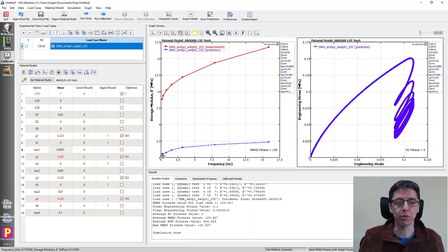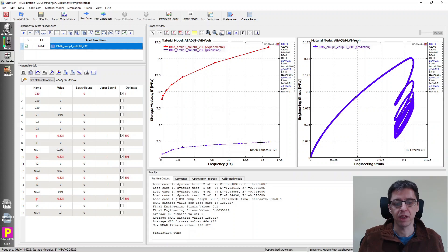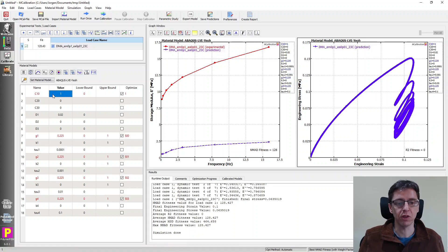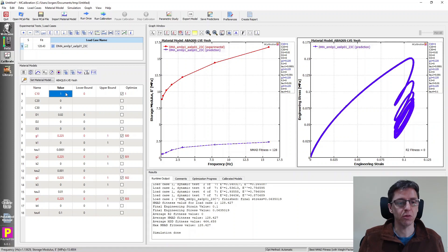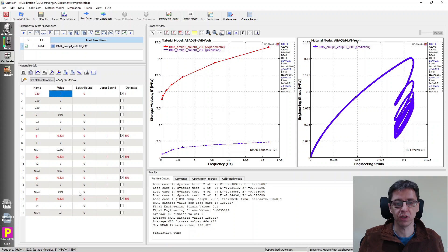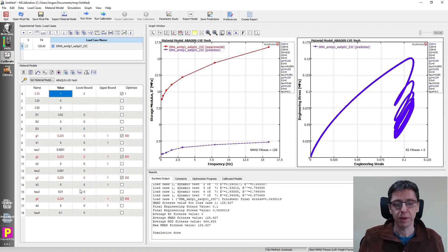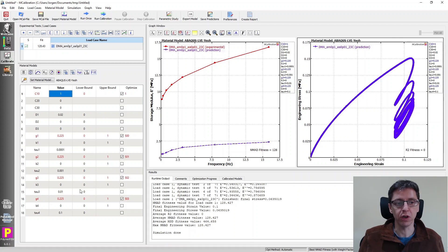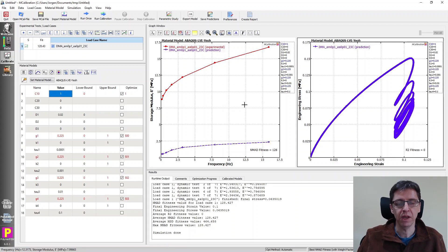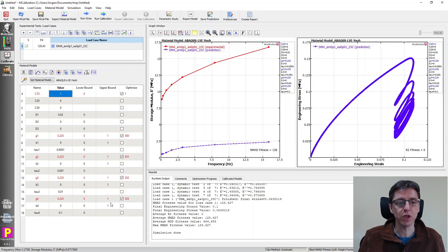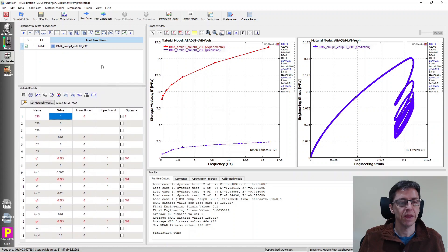We can see now that this predicted storage modulus is way too low. We can change that clearly, the C10 term needs to be much higher. That's giving this point here, they should be instead of two, it should be almost 20. So this should be almost 10 times higher. And then we have to search for these shear relaxation terms. But that's really outside the scope of this little tutorial. All I wanted to show you is how you can import this here and how you set up the calibration. I will have another video later on where I talk about which material model works well for this kind of data and things like that.